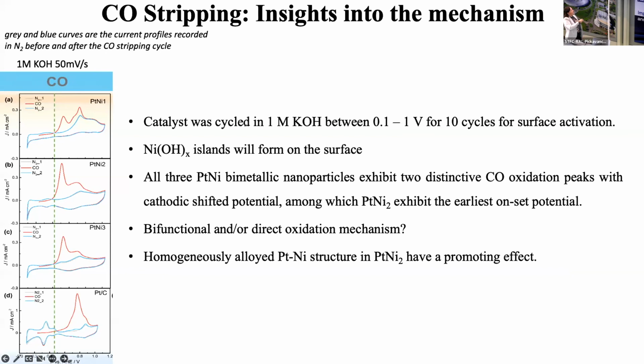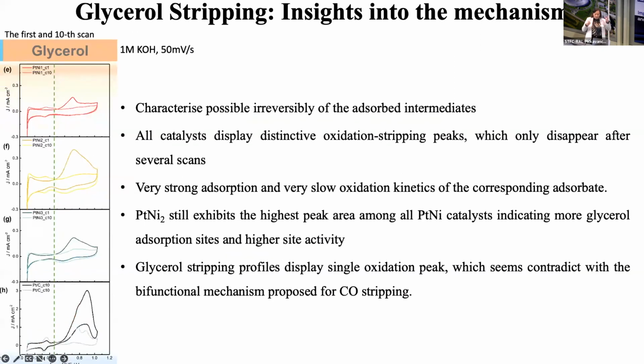What you could see also is that platinum nickel 2 has the highest current if you integrate this, and so it seems that it has a promoting effect. Now, we did this to understand how CO would adsorb and how it would oxidize on this highly oxidized surface. And then we did the same with glycerol. This is the same experiment when we adsorb glycerol on platinum, on platinum with excess of nickel, 1-to-1, and very little nickel.